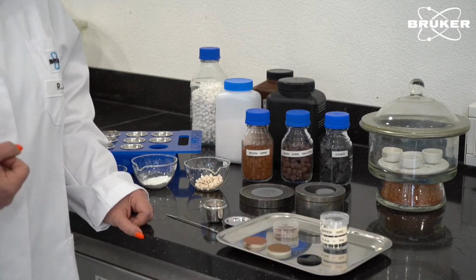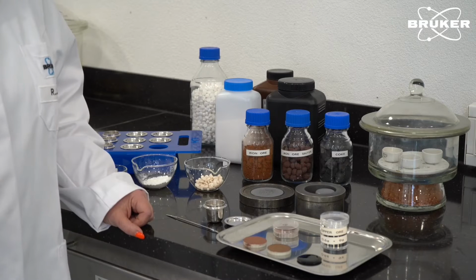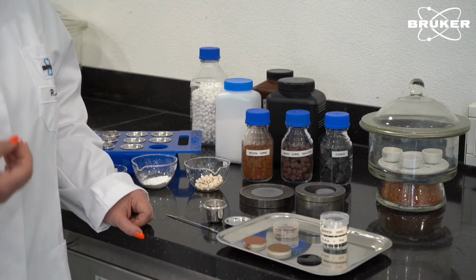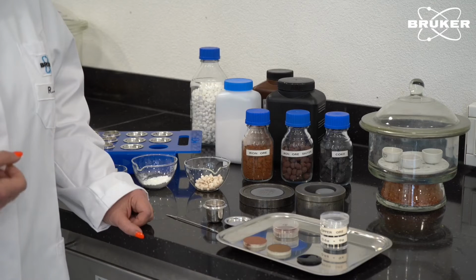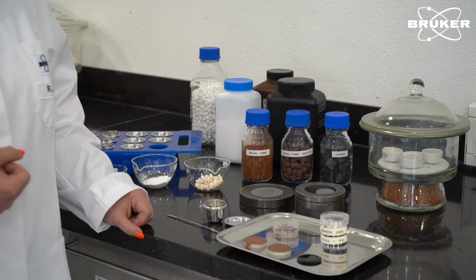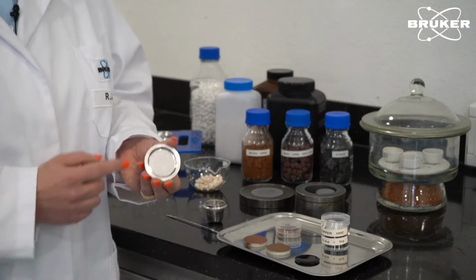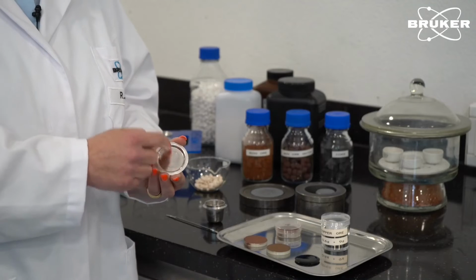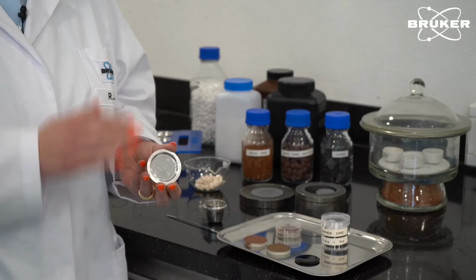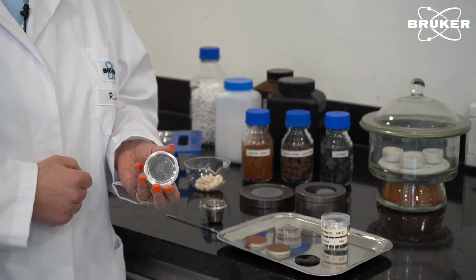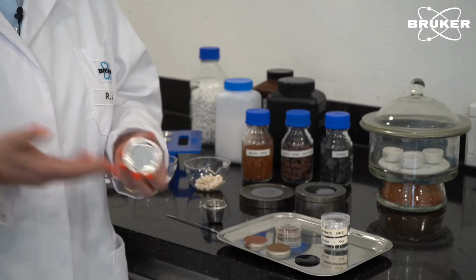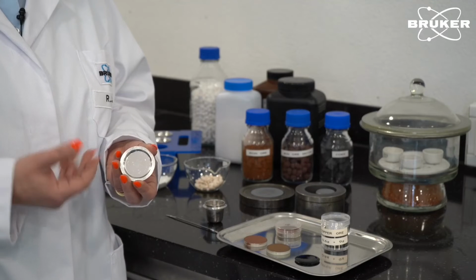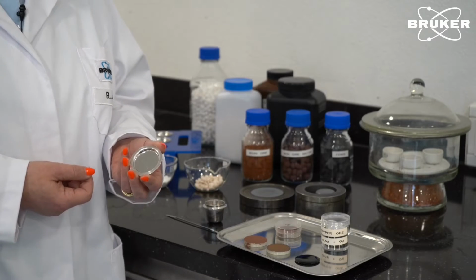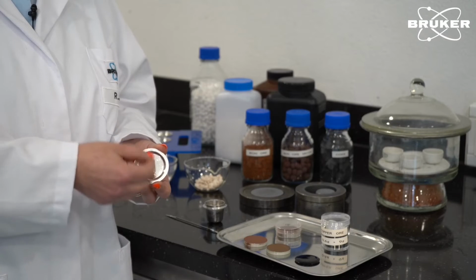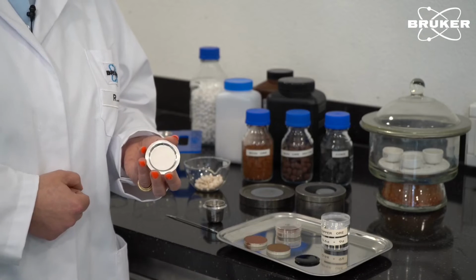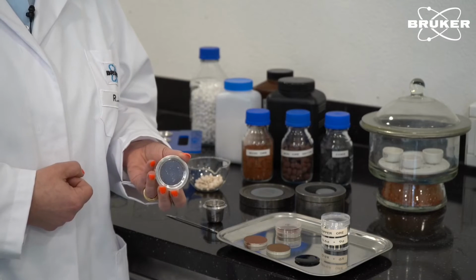Cleaning the crucibles can sometimes be a hard job. In our lab here, we use an ultrasonic bath, and if the crucible is quite dirty, we also add some citric acid just to make sure that the crucible is cleaned. After a long time of use, the molds get a lot of scratches, and this can influence the measurement surface of the fused bead. What you can do is send the old material to the producer, and they will produce new platinum crucibles or molds. But in our lab, we also have a good positive experience with just a little tool which is used with some paste to get the surface nice again. So this is one alternative way to get a nice mold again.